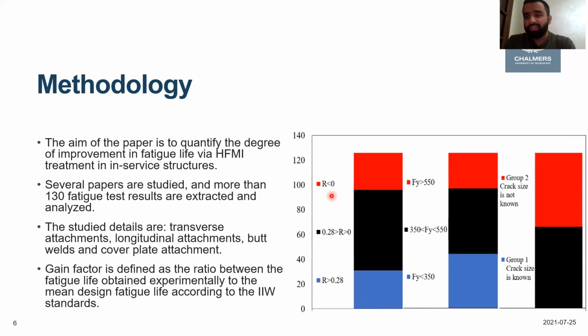And I use these standards in specific because they provide some guidelines on how to quantify the degree of improvement theoretically for different types of details. Here in the figure, you have the description of the studied data pool in terms of the stress ratio, in terms of the studied steel strength, and also the availability of the crack size in the research paper. So you can see that more than half or 50% of the data points contain a description of fatigue crack size, while we also have some papers which do not describe the fatigue crack size. So that requires, of course, different kinds of analyzing or studying.